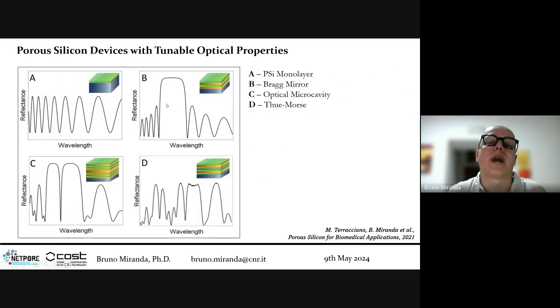Or you can have a Bragg mirror, where you have one layer of porous silicon with high porosity, one layer with low porosity, then again high and low porosity layers alternating. You alternate different layers of porous silicon with different porosity, and you obtain a Bragg mirror that acts as a bandpass filter.